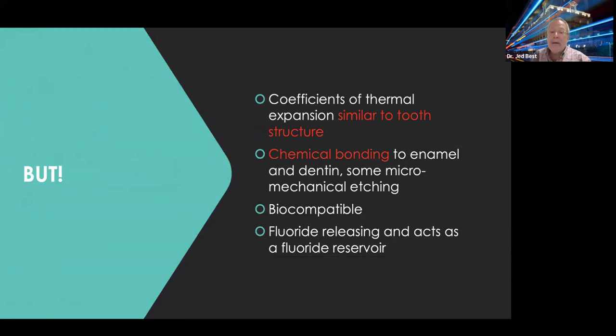But, and it's a big but, their coefficient of thermal expansion was exactly similar to what the dentin structure is. So as the tooth contracts and expands when exposed to cold or to heat, the dentin kept pace. And additionally, most of the bonding is not micromechanical like it is with a resin. It's a pure chemical bond. Now, if you're using a primer, that primer will etch the enamel or dentin to some extent. It's minor, but you've got pure chemical bonding and keeping the seal of the dentin intact. It's also biocompatible, and it also releases fluoride.